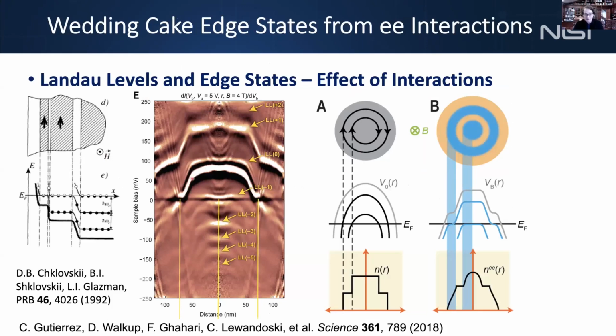Now this hat shape is just the compressible, incompressible strips that I talked to you about in the beginning, which were predicted early in the quantum Hall research. So what's happening is that the parabolic potential here is getting reconstructed due to the fact that when I form these Landau levels, I have a high density of electrons, I have a high electric field. That's going to bend over the potential, and you're going to reconstruct the potential in this form here. This is shown by calculations. You can find them in this paper that we published.